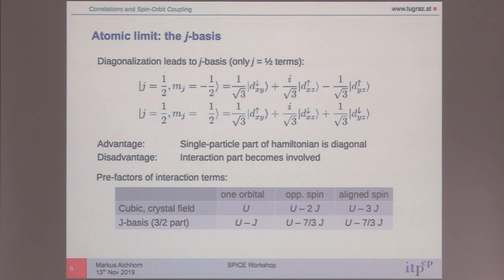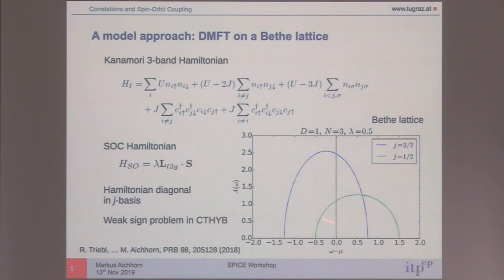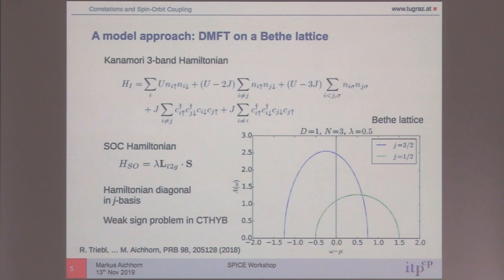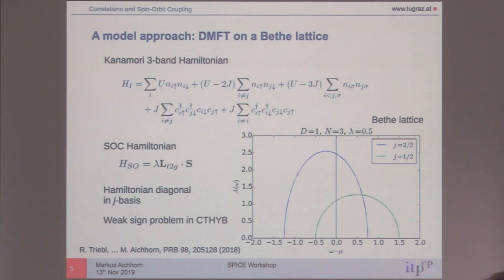The point is: you can think of this as a crystal field within the T2G coming from a tetragonal distortion — like a Jahn-Teller effect. Without interactions, spin-orbit coupling gives a splitting of 3/2 lambda. A tetragonal crystal field gives the same splitting with delta. If you set all interaction parameters to zero, you get exactly the same results for observables. The key clarification: no term is ever neglected in the actual calculation — this simplification was only for the analytical argument.